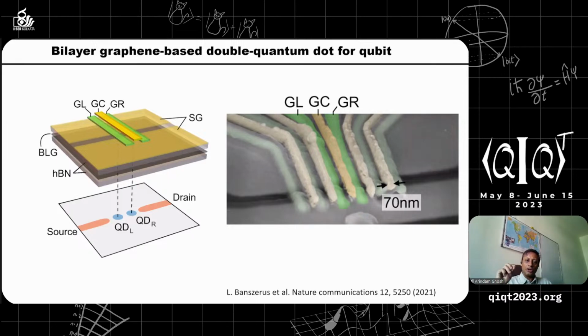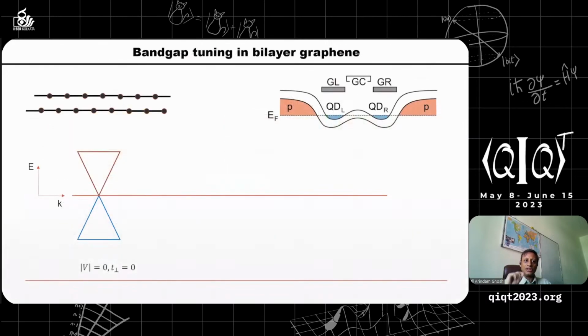See, graphene has a lot of advantages. Graphene has very weak spin-orbit coupling, so the dephasing is low, and you can make carbon extremely pure without too many magnetic impurities or atoms with magnetic moment, so that you can actually look for very high dephasing time. Which is why many people are trying to look for this kind of platform for qubit formation. But in the case of bilayer graphene, there's some unique advantage.